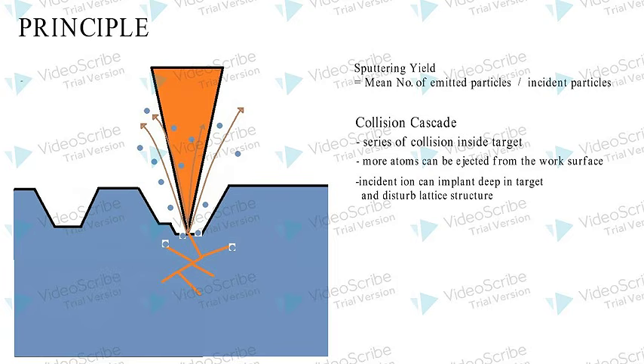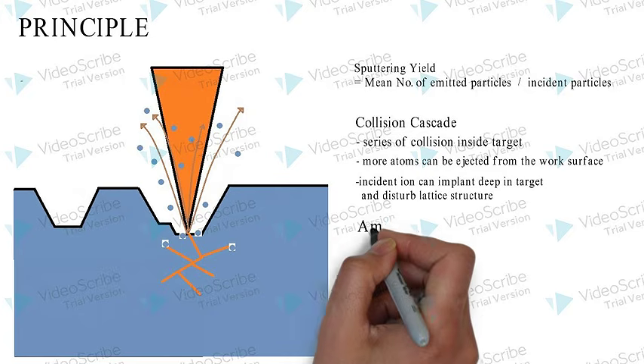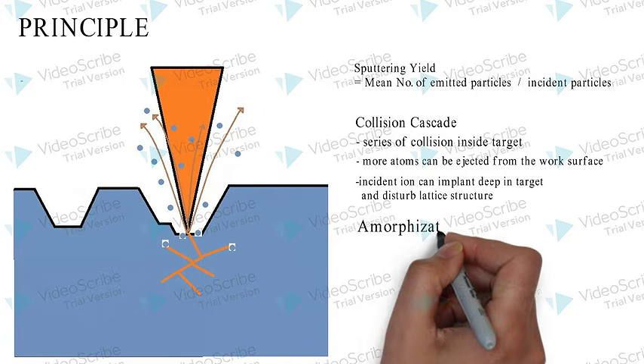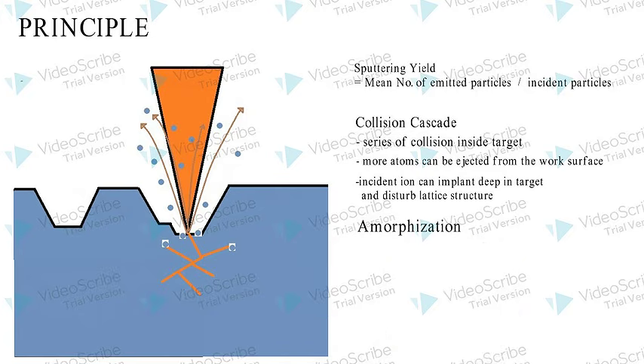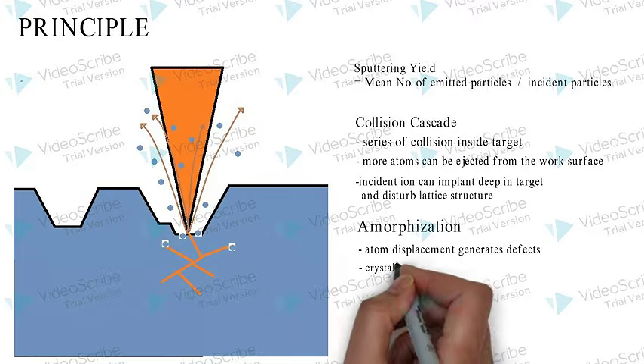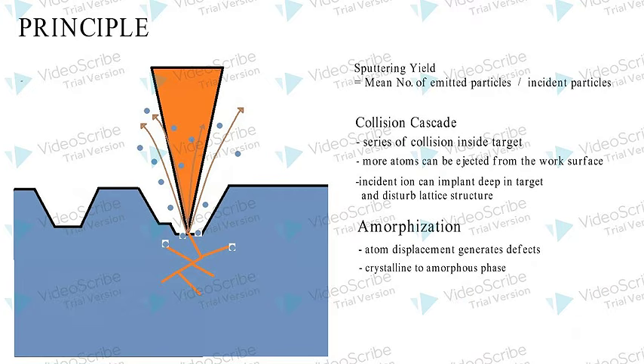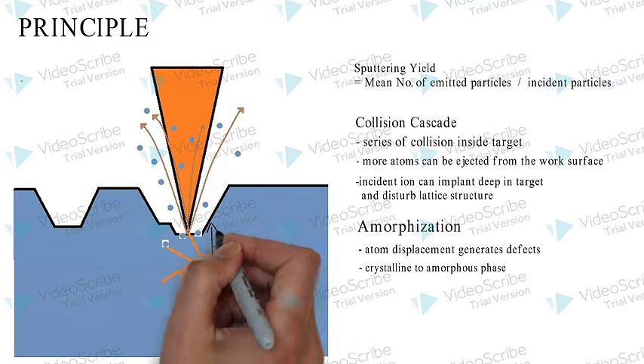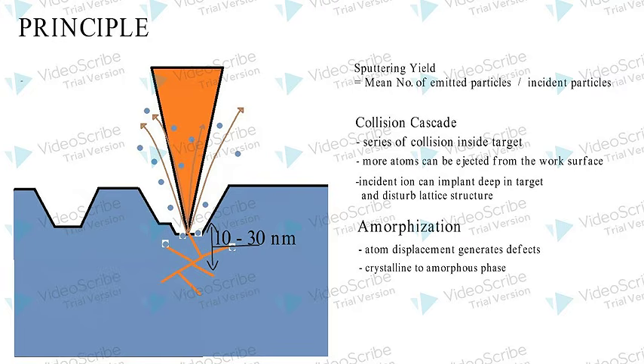As we surely know, one problem gives rise to another. If collision cascade occurs, the ions can get implanted deep in the surface of the workpiece to be machined. This can cause point defects in the crystalline structure of the workpiece, and that causes the crystalline structure of the workpiece to convert into an amorphous structure, which can be harmful at times. The depth of this is very small, 10 to 30 nanometers, but as this is a micro machining process, it affects.